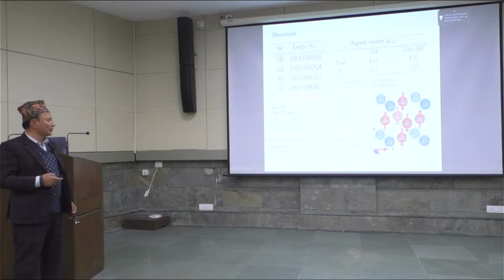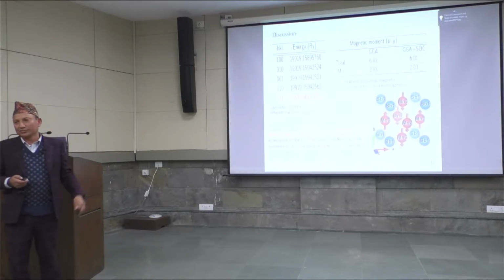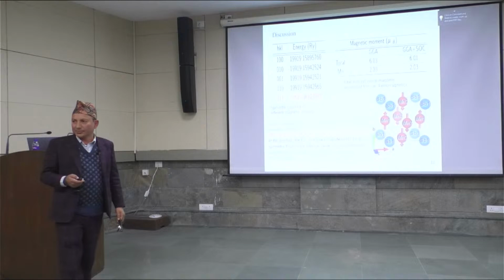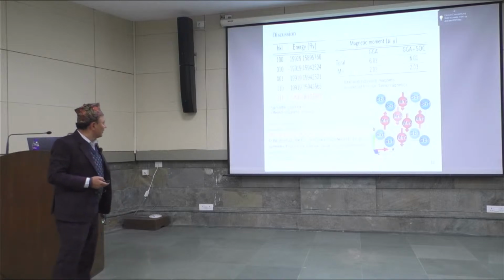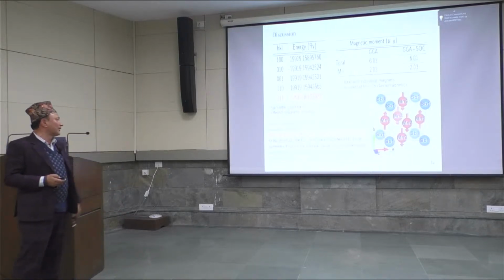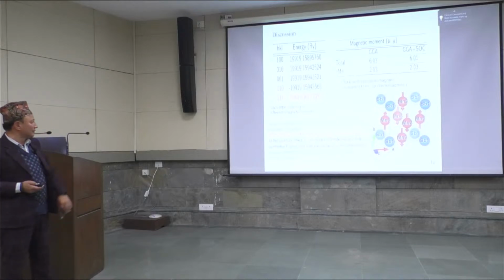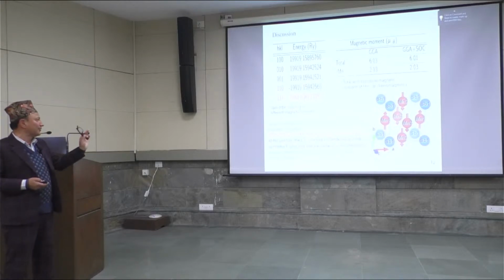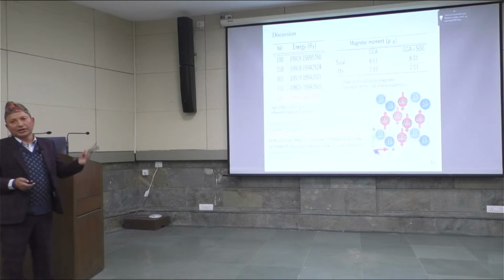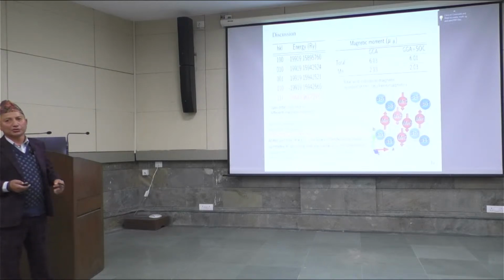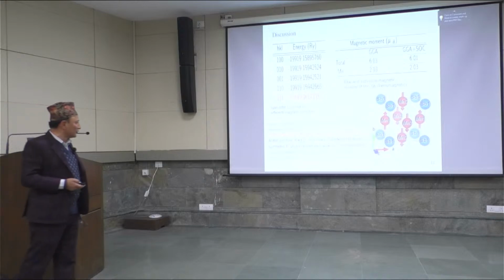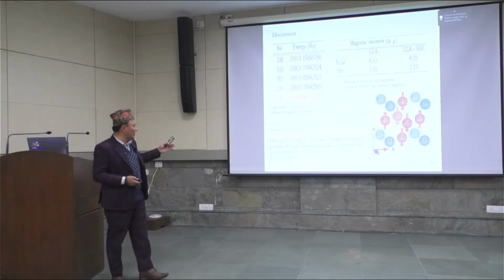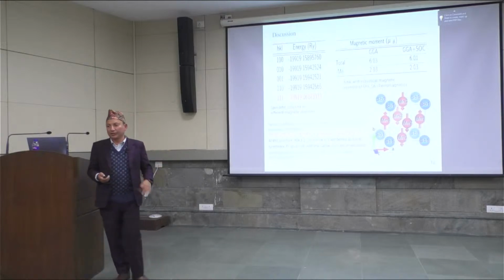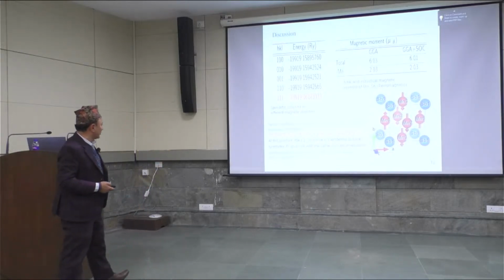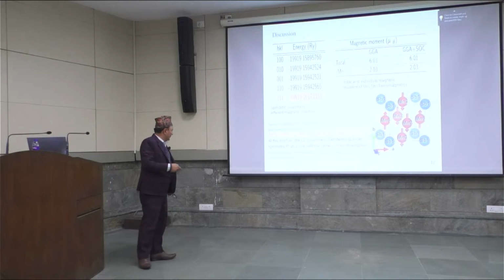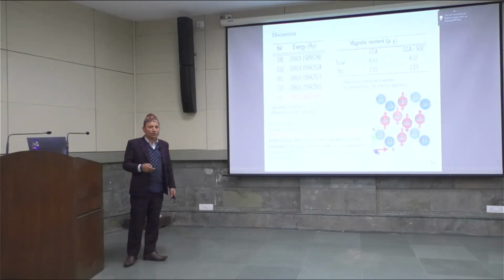Still, what we are seeing does not match the neutron diffraction experimental results. So we used spin orbit coupling in different magnetic directions, and still we get the ferromagnetic order. Then we thought about why this happens. So there we used unequal magnetic moments of the Mn atoms on different sites.